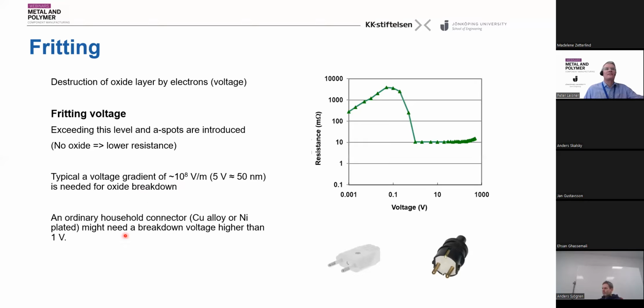And this also means that in ordinary household contacts, like you see them here to the right, which are made of copper alloys or maybe nickel-coated copper alloys, it's quite normal that you use 1 or several volts to break down the oxide film. And that's of course no problem when you have 240 volts in the system.